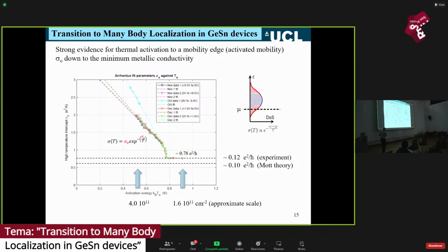So from the fits, we've got lots of data on this. If we fit the temperature dependence of the conductivity, we extract two parameters, sigma naught, the prefactor, and T0, where k_B, the Boltzmann constant, times T0 would be the activation energy. All I've done now is plot from all the different fits, lots of data sets here. I've plotted them all out.